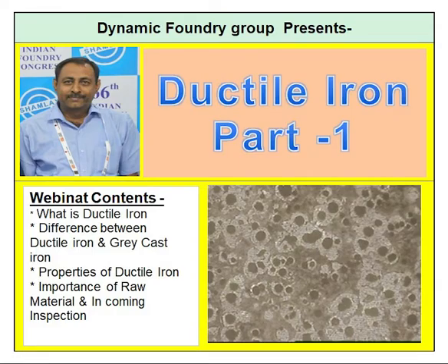Charge mix. Let us start with the charge mix. In ductile iron, the most important factor in making ductile iron is the selection of charge mix and scrap. That is very important. Selection means basically we are normally using CRCA and home returns and rejections, because normally we are not using pig iron, because ductile iron grade pig iron is not available in most parts of India, so we are normally not using it. So CRC, home scrap and rejection are the major things we are using. So control on CRC and home scrap is very important here.